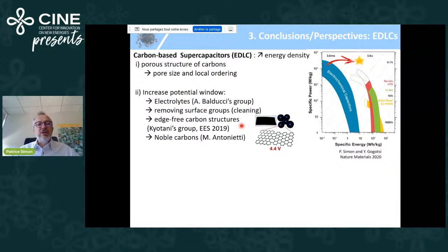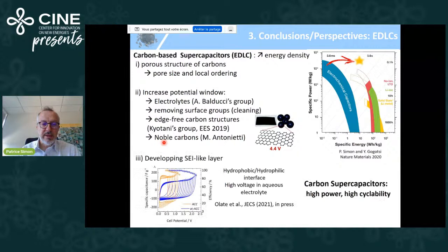And you can also prepare edge-free carbon structures. This is a Kyotani's group with a very nice paper up to 4.4 volts, using noble carbons from Markus Antonietti with very high stability. And I would say also a last result that is going to be published soon. It's in press. You can develop SEI, solid electrolyte interface-like layers onto porous carbon. This is a work of Marco Olate, sorry, there is a mistake here. And you can see from this paper from Olarte that this is a porous carbon in aqueous electrolyte without any specific treatment, so 1 volt maximum.